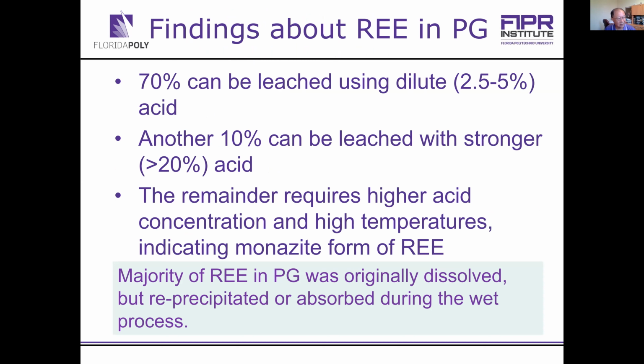Phosphogypsum is another major product, waste or byproduct, containing rare earth elements. So we also studied the occurrence of these rare earth elements in the phosphogypsum. Many research studies, including our research, indicated that in the acidulation process in the chemical processing plant, the rare earth elements in the phosphate rock report up to 70% to phosphogypsum and 30% to the phosphoric acid. But most of the rare earth elements are actually initially dissolved.